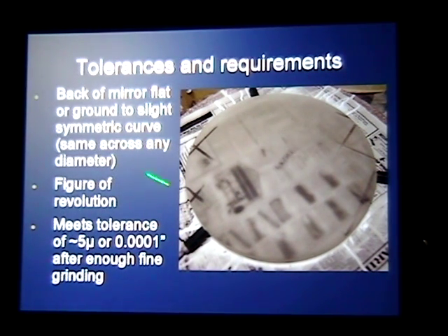Now the same, of course, goes for whatever's underneath the mirror. The turntable needs to be quite flat. I try to get it down to thousandths of an inch. And you also put a squishy layer between the turntable and the mirror. And you typically will rotate the mirror to different angles as you do the work, so that if there is a little bit of curving due to the polishing pressure, then it's sort of randomly distributed. And generally that will keep you from grinding any astigmatism into the mirror.